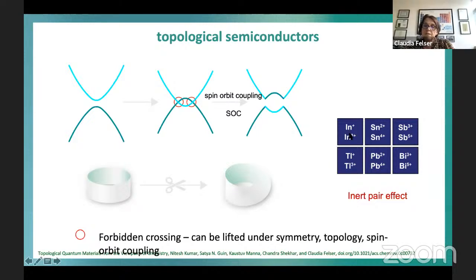Indium is in group 3 and tin is in the same group as silicon, group 4. These heavy element compounds have a different valence compared to the same group elements which are lighter, because here we have the so-called outer s electrons, the 5 or 6 s electrons, which are valence electrons. Because of relativistic effects, they get contracted, and therefore the atoms don't like to give them away because they are now very close to the core.